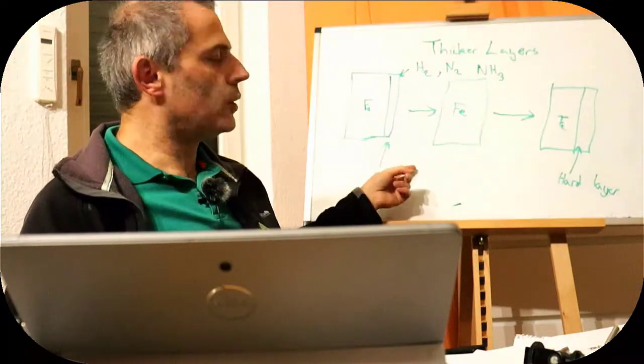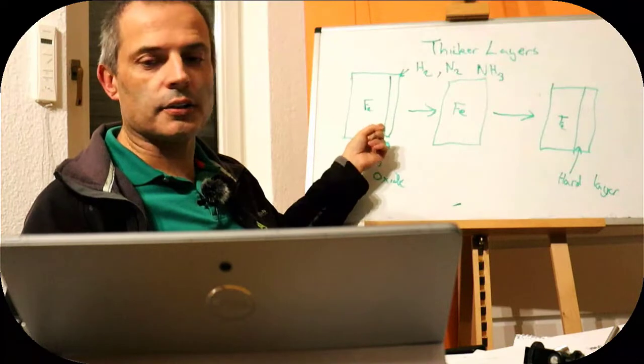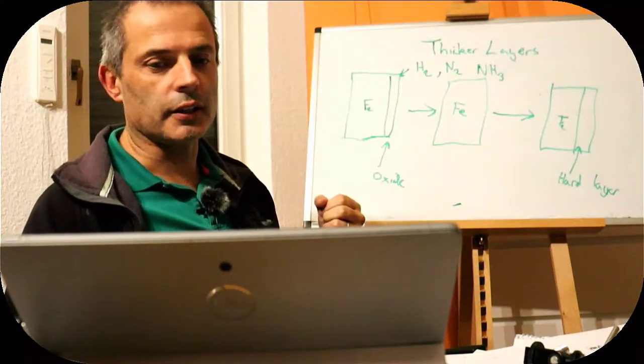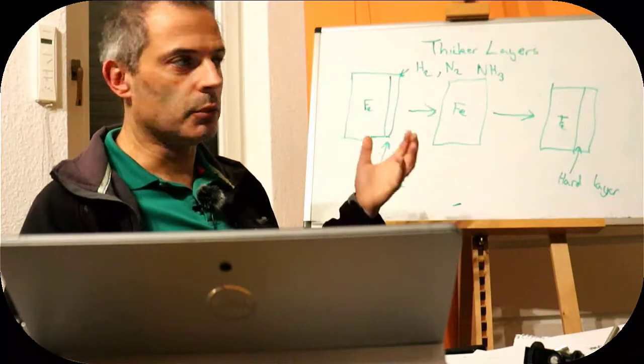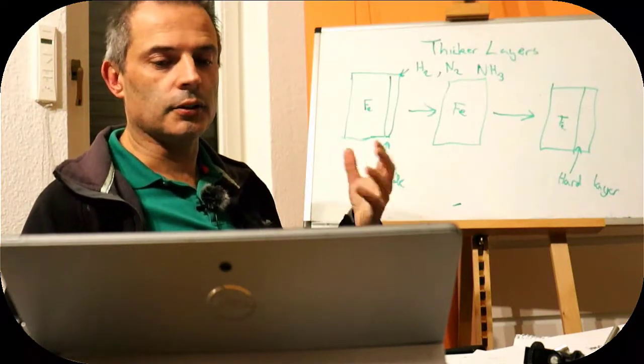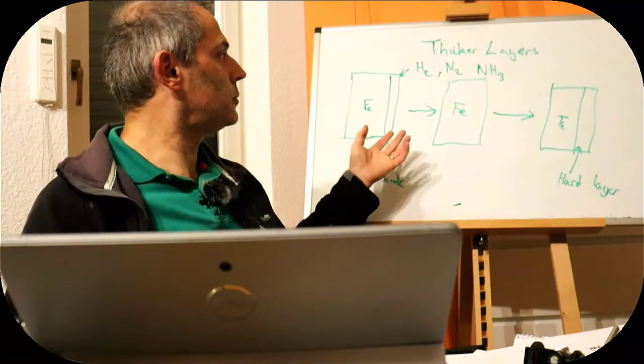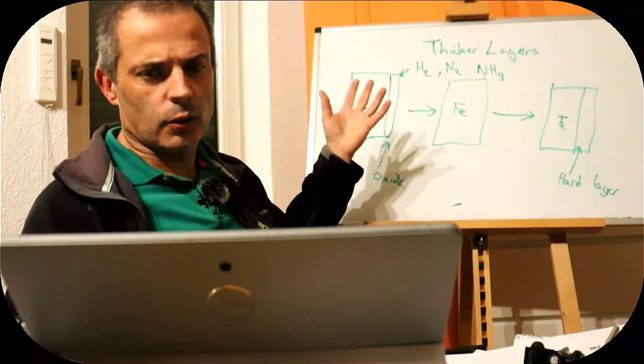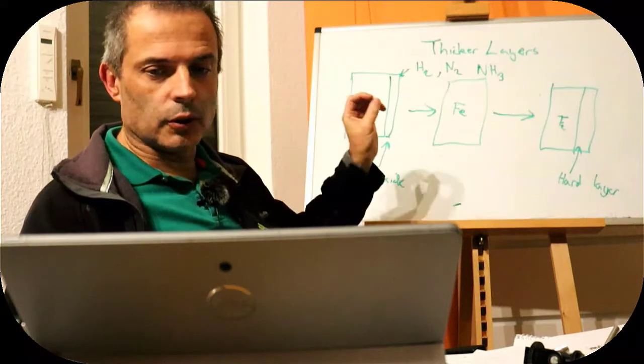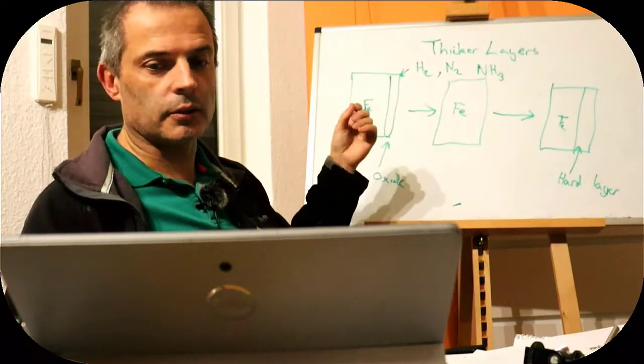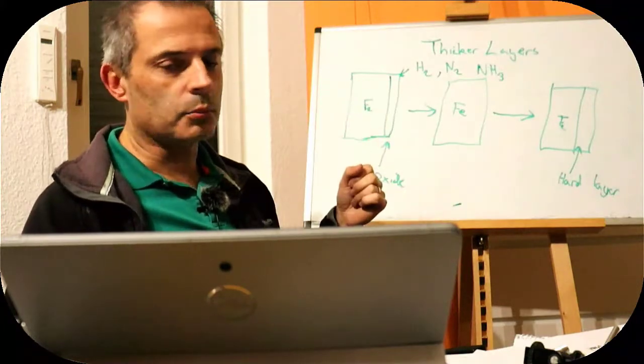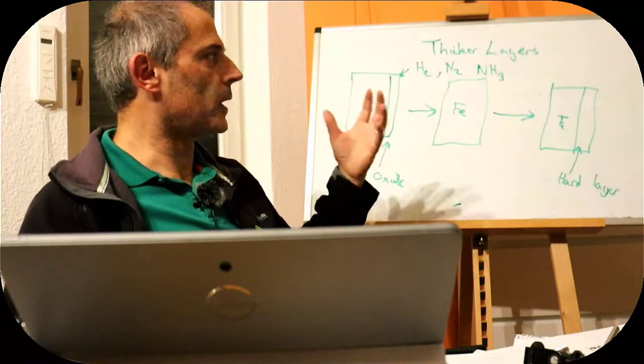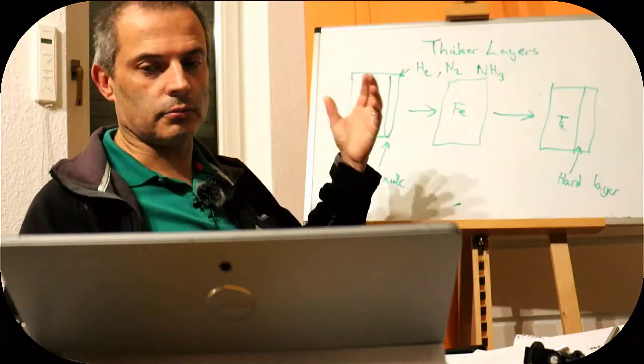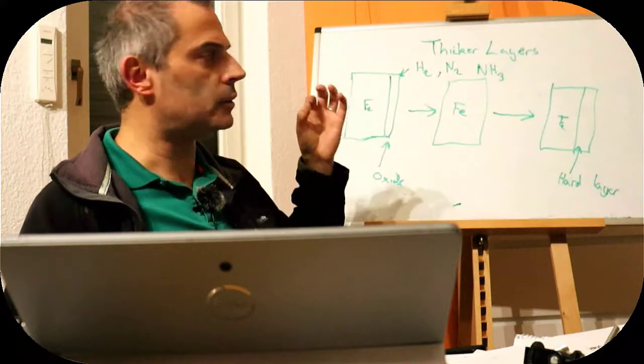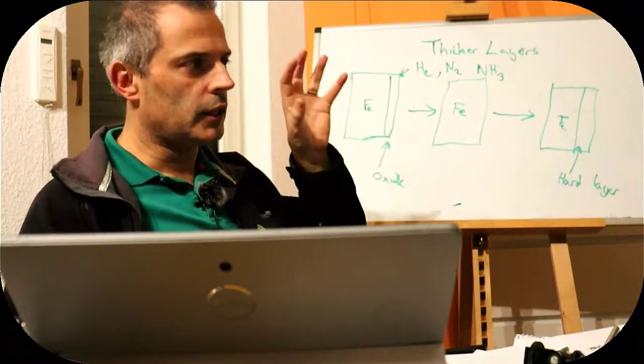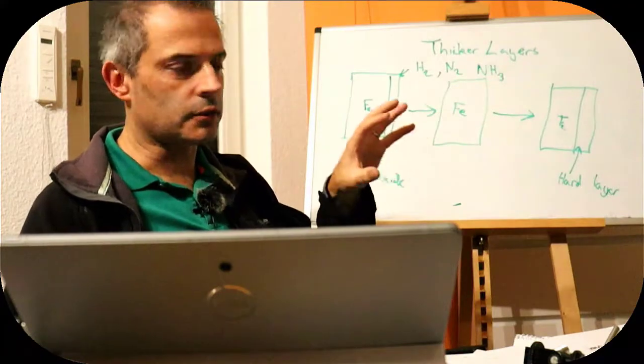And if we do that, we can address this oxide layer. So we can remove an oxide layer that's a little bit more robust, something like aluminium oxide. If we make it thin enough, using a wet etch method to get it thin and keep it cold, then we can knock it off with a plasma or an ion beam of argon, for example, and then we can add our nitrogen afterwards. It turns out that even argon ions that are not so reactive will also harden the surface of a metal, because effectively we are introducing errors into the surface of the metal.